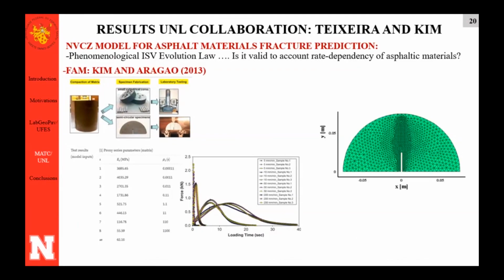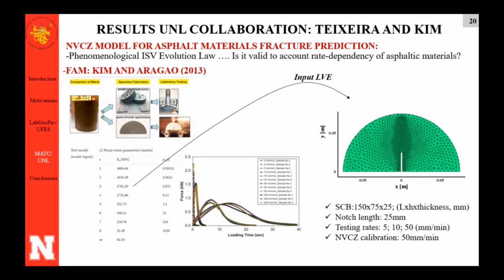So I simulated the same test that the authors did here. I input the linear viscoelastic properties that were available from this reference. And basically the geometry of the beam was 150 by 75 high and thickness 25, had a notch length of 25 millimeters, and they tested 3 different rates. So what I did was I took these tests and calibrated for 1 rate, 50 millimeters per minute. Then I used the same parameters to predict the behavior at 2 other rates.